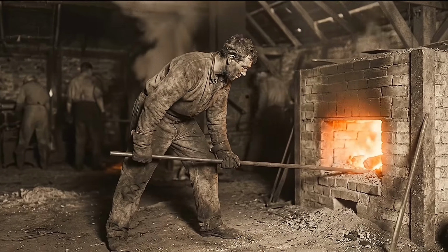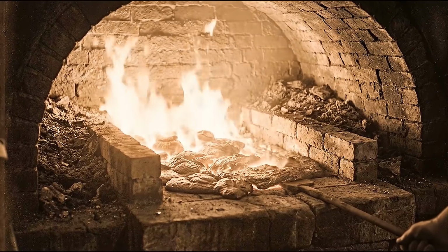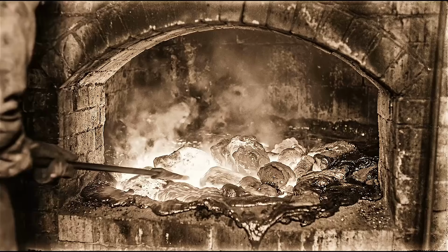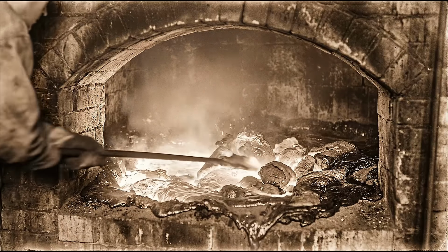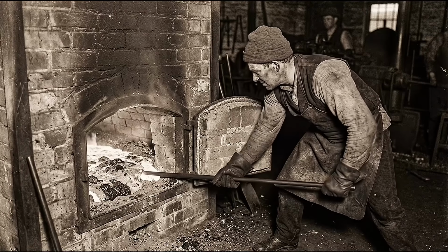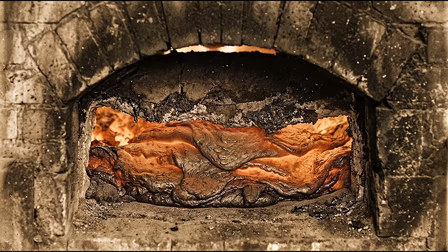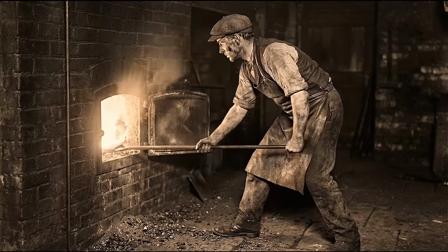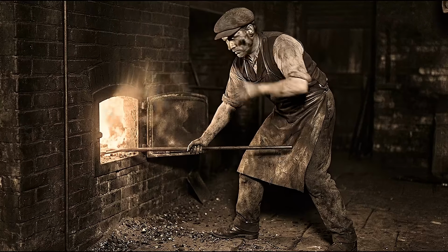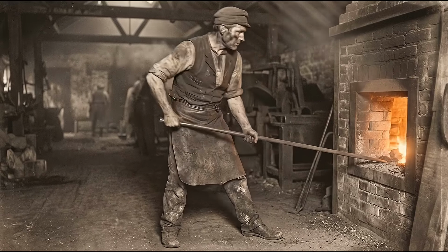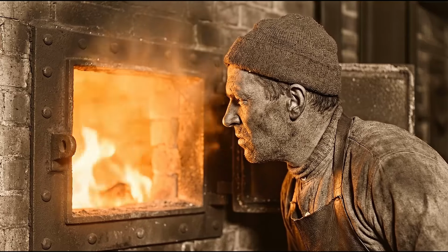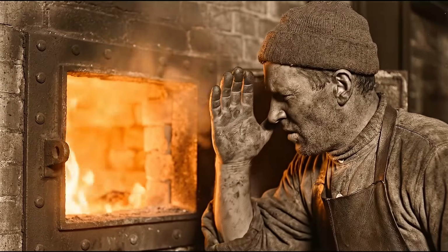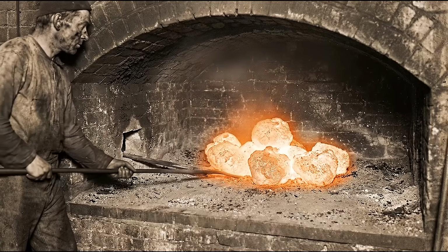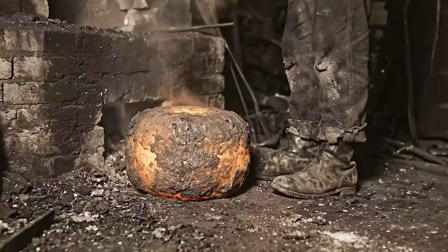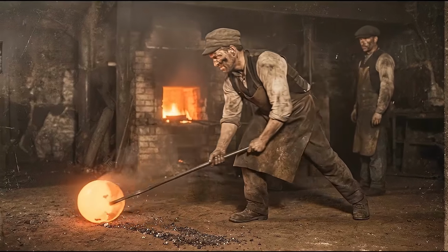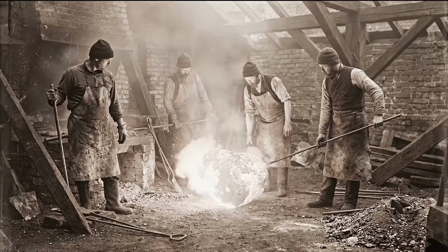Because here is the chemistry that made this whole process so physically brutal. As carbon left the iron, the melting point of the remaining metal climbed. Pure iron melts at a much higher temperature than high-carbon pig iron, so the cleaner the iron got, the stiffer it became. What started as a liquid pool slowly turned into a thick, sticky paste, and the puddler had to fight his bar through heavier and heavier resistance with every passing minute. 2 hours of this, sometimes 3. His arms and back absorbing the strain while his face sat inches from a furnace hot enough to blister skin from a distance. Eventually, the iron came together in large spongy masses called puddle balls, each one weighing roughly 80 to 90 pounds. The puddler hooked them onto the end of his bar and dragged them, one at a time, out of the furnace and onto the foundry floor.